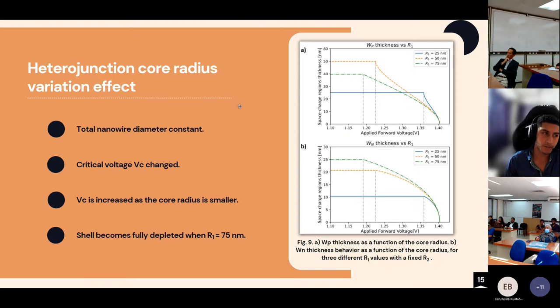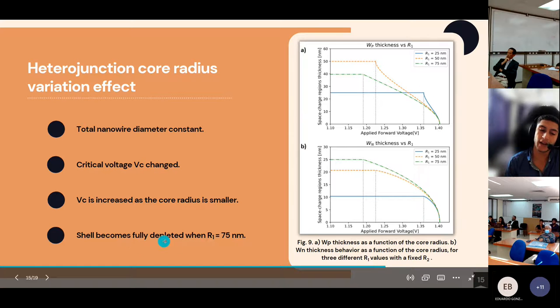Heterojunction's core radius variation effect. The total nanowire diameter is constant at 100 nanometers. The critical voltage changes when we take R1 equal to 25 nanometers and R1 equal to 50 nanometers. The behavior of the critical voltage is that it increases as the core radius is smaller for these two cases. On the other hand, when R1 is equal to 75 nanometers, the shell becomes fully depleted when this is the inner radius.